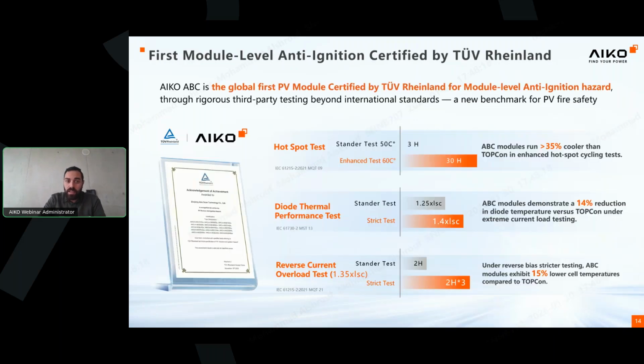First one, the hotspot test. The standard test is done for 3 hours at a temperature of 50 Celsius. We did it with our panels in a more advanced and strict way: at 60 degrees for 10 times the time, 30 hours. As a result, it was found that our panels are 35% cooler than the TOPCon panels. So this is the first improvement, the hotspot test. The other part was the diode thermal performance test, where they apply 1.25 of the short circuit current. We did it with even stricter conditions, 1.4. The result showed a 14% reduction in the diode temperature. So this is the second improvement.